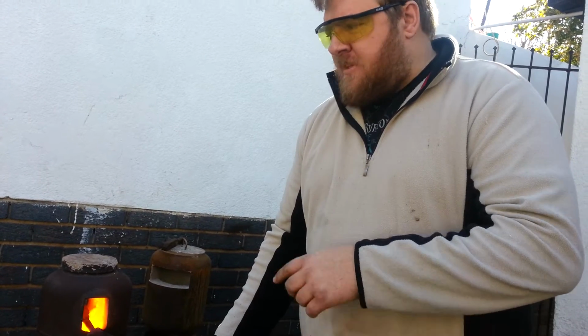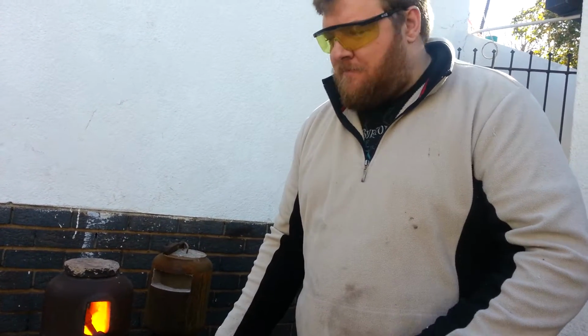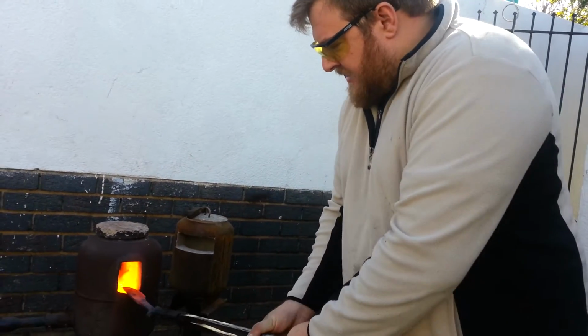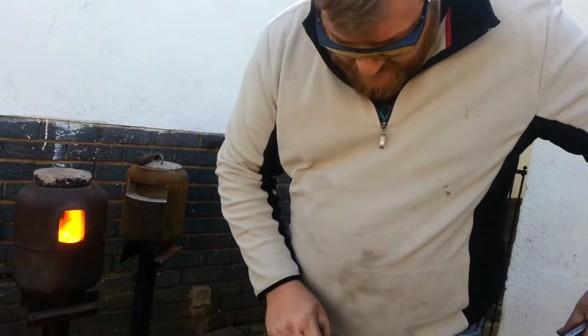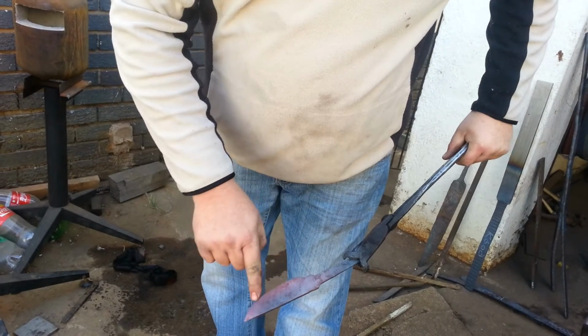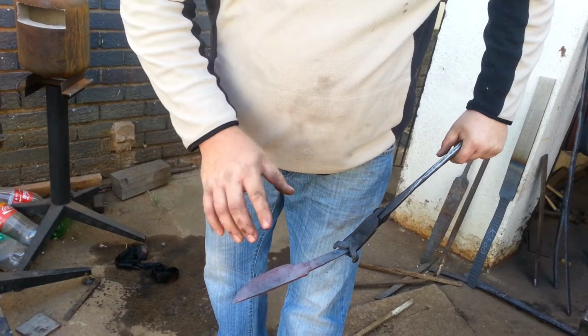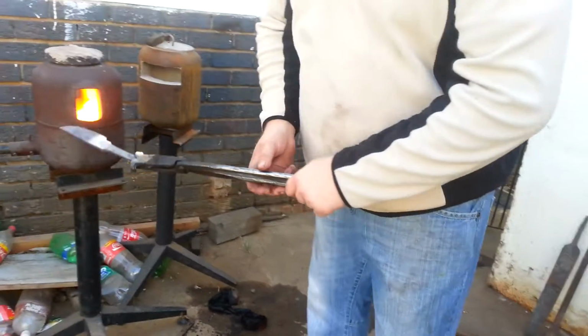Now, when you're forging multiple blades, you can put one blade in, forge one blade, put the next blade in, forge the next one when it's hot. Never do more than two at a time, because a piece of steel that sits in the forge for too long will get too hot, it will cause grain growth and your steel will become brittle. It can be fixed, however, if you do multiple normalizing cycles, but we want to avoid that because it tends to become a waste of time if you don't focus and concentrate. Now you can see here the steel is heating up. It's got orange along the edge, but because the material is thicker along the back, it creates a heat sink, we want to get that heat nice and even.